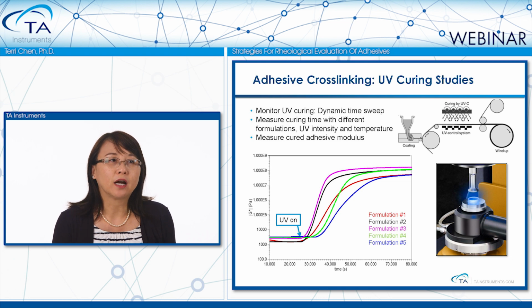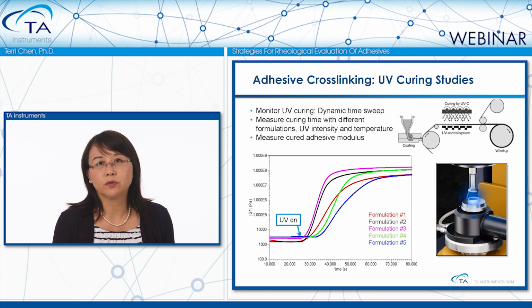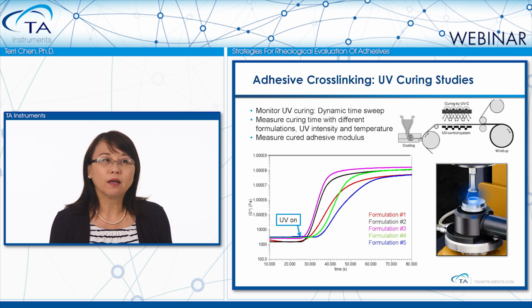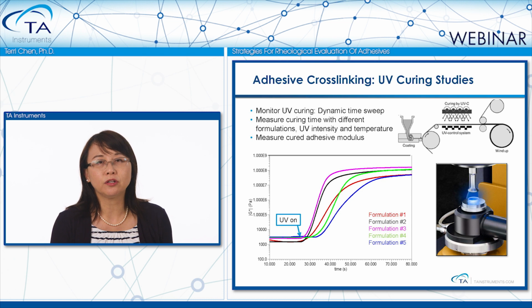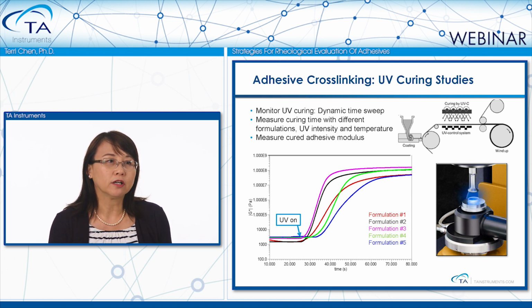Many adhesives are cured or partially cured through heat, UV radiation, or under humidity. A dynamic time sweep experiment is typically used to monitor curing. This following figure shows an example of using a UV curing accessory attached to a DHR rheometer.